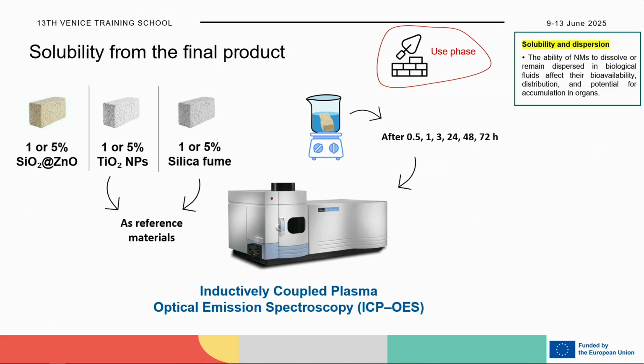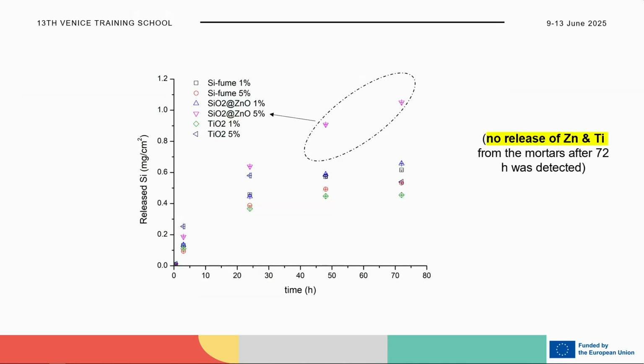Last but not least, we also look at the solubility from the final product, actually the mortar. So in this case, we compared the solubility of our advanced material that was embedded in the mortar. And as reference materials, we used 2 different materials, one based on titanium dioxide nanoparticles and the other on silica fume nanoparticles. Again, we look at the solubility over time according to the time points that are used in toxicity testing. And what we observe here is that there was no release of zinc or titanium in all the samples, so this was good. And we observe only the release of silica, as you can see here.